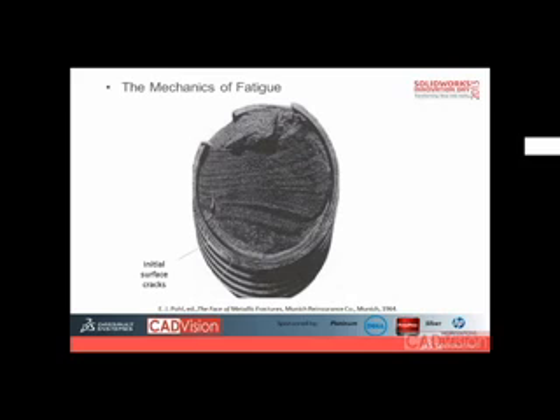The micro cracks, after repeating cycles, form quite a lot of cracks on the surface, and what happens is they start to extend in the middle. We call these ratchet marks, and after a period of time again, suddenly they combine together, and we have this kind of beach mark, some sort of wave forming along the surface. At this stage the crack grows faster and faster, and finally we see something that is not really nice to see. That is the final fracture region. This is typically the last section where the part fractures. So we see some sort of coarse surface there.